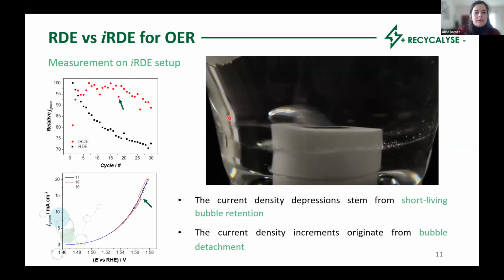And this can be very nicely seen in this video. We see the bubble is formed and poof, it gets detached from the surface of the electrode. And this video corresponds to scans 17 and 18, and we can see it also on the forward scan. Here, shown by this arrow, we see an increase of the current density, which corresponds to the bubble detachment.